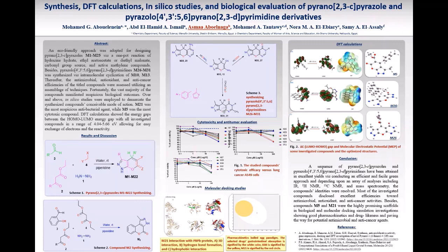DFT calculations showed the HOMO-LUMO energy gaps for all investigated compounds in a range of 4.04 to 5.66 electron volts, allowing for easy exchange of electrons and reactivity. By measuring the chemical hardness, the resistance to change of the electron cloud density of a chemical system, it was found that M5 and M8 had the lowest values compared with the other investigated derivatives, at 2.029851 electron volts and 2.193255 electron volts, respectively, while M20 had 2.76034 electron volts, with a high hardness value which makes it a more stable, less reactive compound.